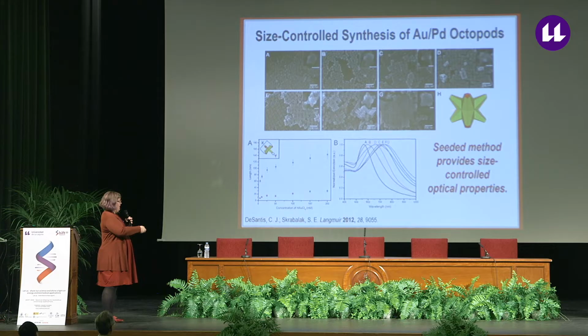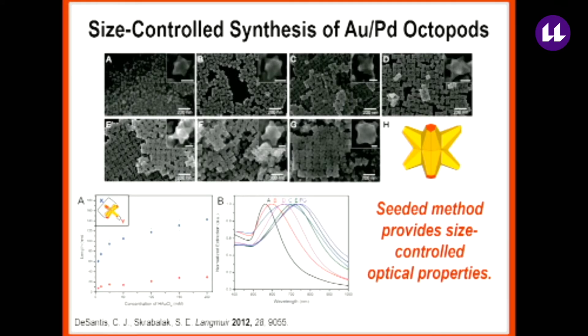It's straightforward with this synthesis to tune the size of the branched nanocrystals. We just change the number of seeds available in the solution relative to the amount of metal that can deposit. And as you have more metal depositing per seed, you get larger branched nanocrystals, which results in a redshift in the LSPR.